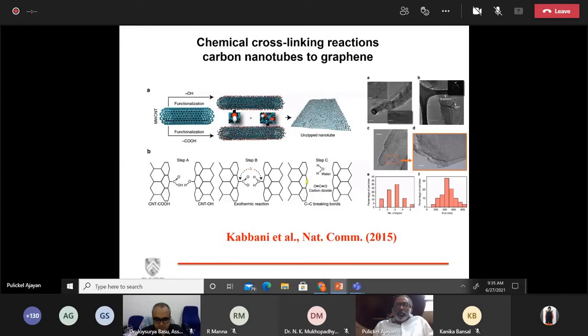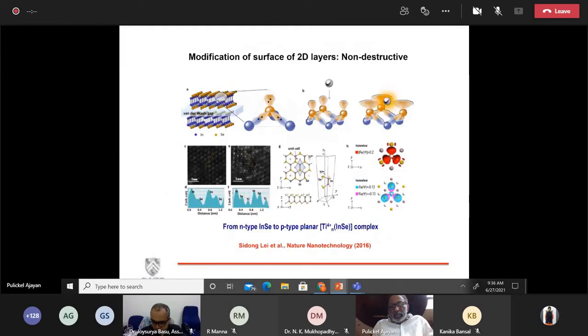The other possibility is to actually create cross-linking. And again, this is a very interesting experiment where we took these building blocks with different surface functionalities and then connected them either through mechanical force or through laser radiation, and we were able to actually create reactions between the functional groups that are attached to different building blocks. And by using that, you can get different types of carbons by introducing these types of interconnections. Now, many of these chemical changes at the interface are done by breaking bonds, so the topology of the system can change by doing that.